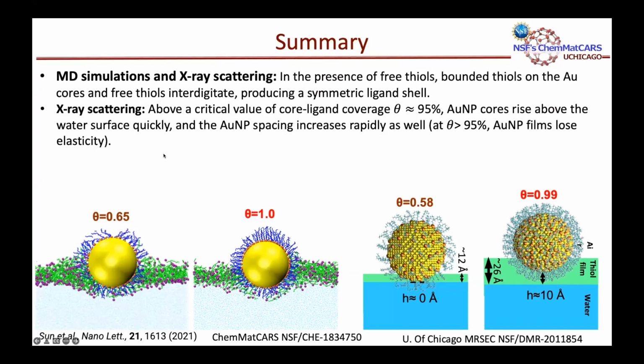So in summary, the MD simulations and X-ray scattering show that in the presence of free thiols, the bonded thiols and the free thiols interdigitate, producing a symmetric ligand shell.